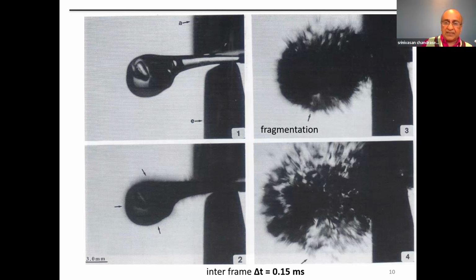What you can tell from this is that the fragments come out at about 20 meters per second. These are the particles, they fly out. You can also get the velocity in another way, which is you break the drop and you look at how far the fragments have gone and fallen on the floor. And just by measuring distances and using simple, high school physics, you can estimate the velocity of the fragments. And surprisingly, there is very good agreement between what you see with the high-speed photography and the fragment velocities that you get by just mopping them off the floor and measuring distances.